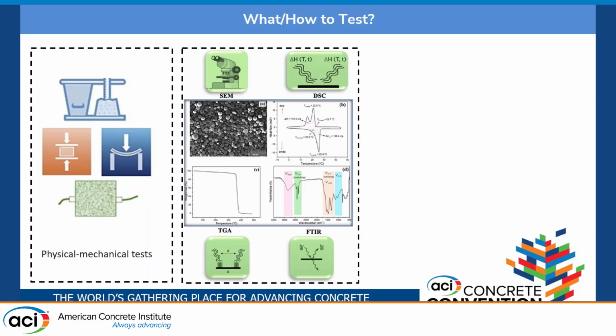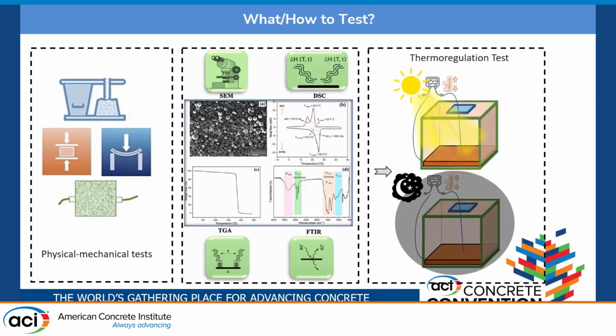We're looking also at the TGA. We're trying to understand how thermally stable these materials are, and we're using some FTIR to see the chemical structure and chemical interaction between these materials that we're producing, and we do some surface morphology through the SEM and EDS. Finally, this is a very novel and unique approach that we are using. We are using a thermoregulation test. This is a custom designed test cabin.